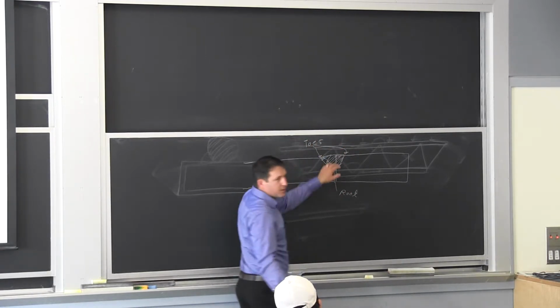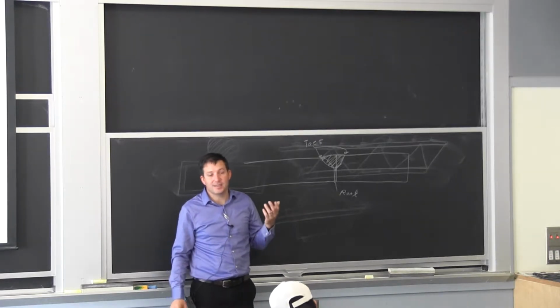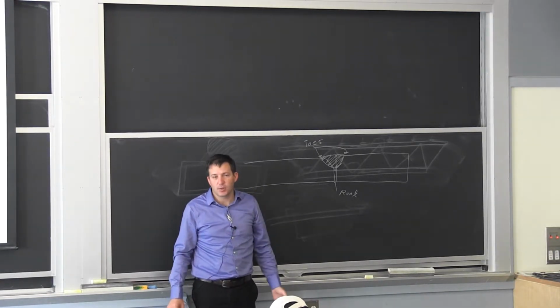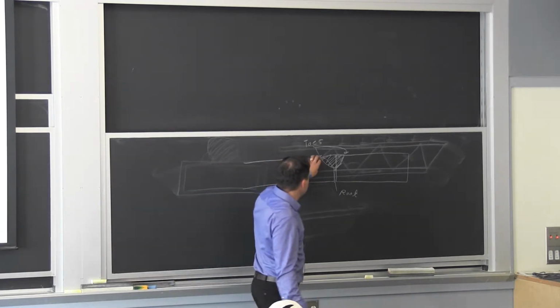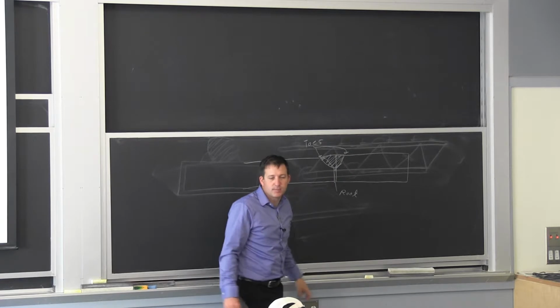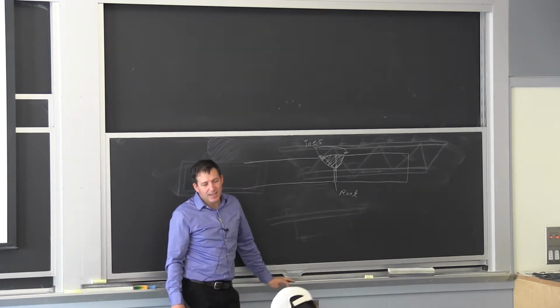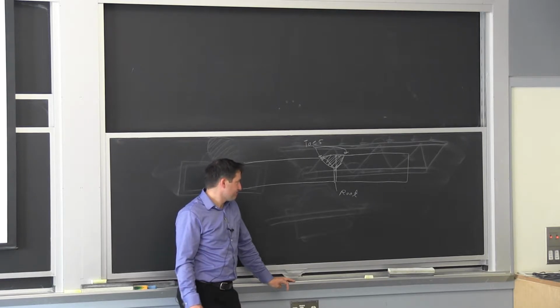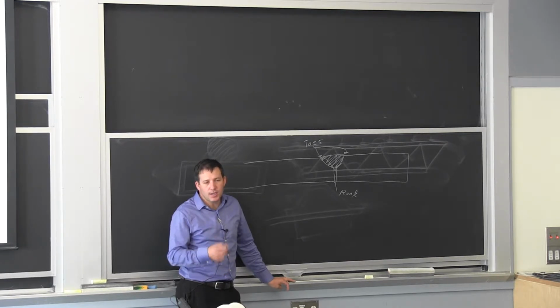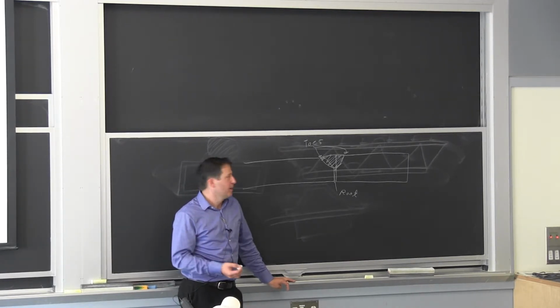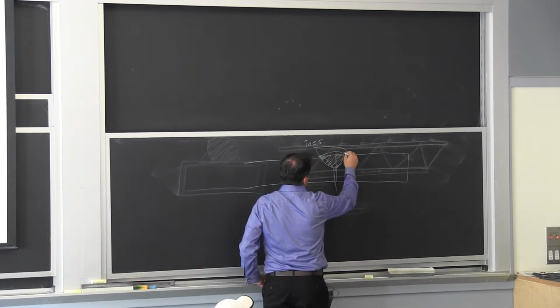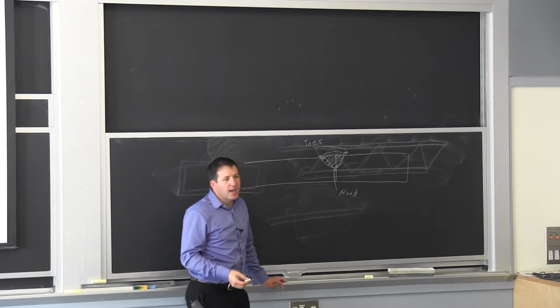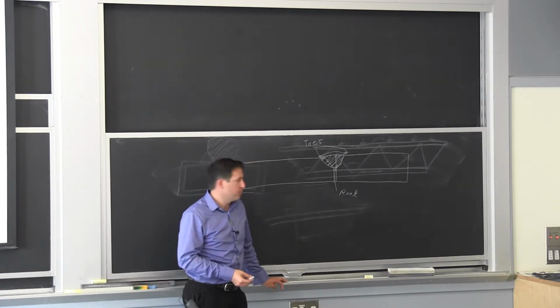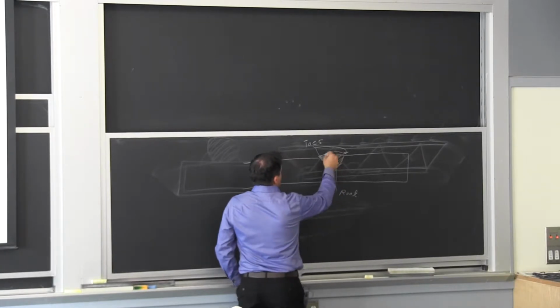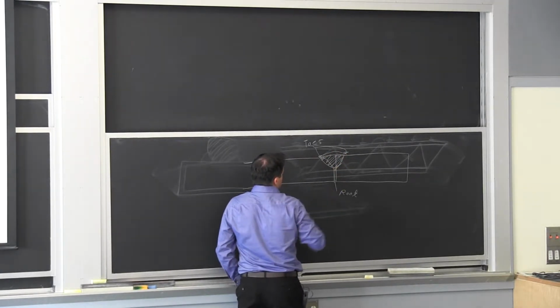Now, I melted this, so I know that I form essentially a casting here. I'm going to have dendrites. I'm going to have some segregation. One thing that we were talking about Friday in detail is we need to protect that molten metal when it's melted. We talked about slag, which will help keep the purity in the alloy. Any impurity is attracted by the slag and will be on the surface as you weld, or you use a shielding gas so you don't have contaminants coming into your melted pool. That's really important, and it's only affecting the strength and the ductility of what's being melted.